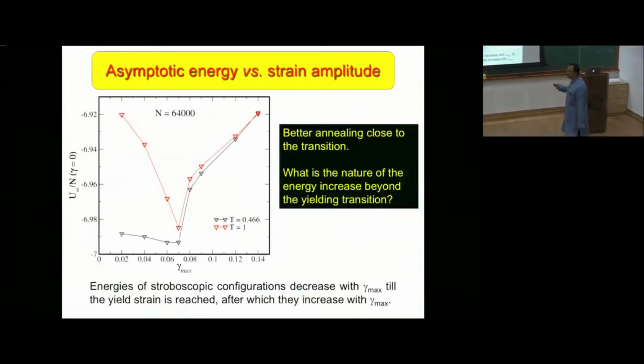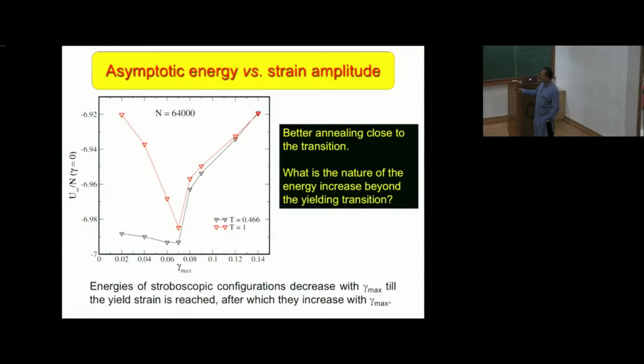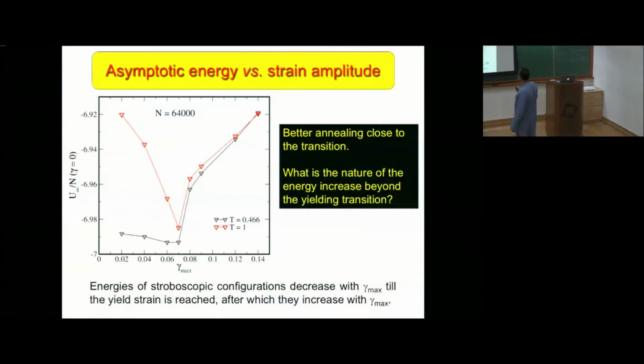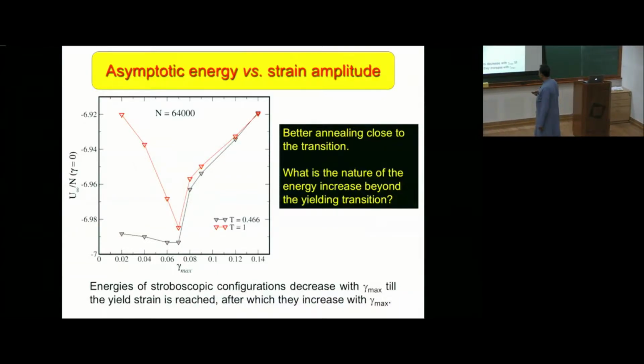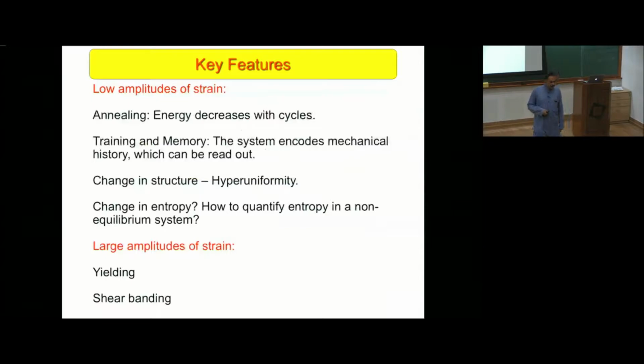So this is now the summary of what we said about the annealing behavior. Below yielding, you always anneal better and better as you increase the amplitude of deformation. Above, you don't. But on the other hand, above the transition, you seem to have a quote-unquote ergodic state, in the sense that the final properties of the system don't seem to depend on initial conditions, which is not true below the yielding point. So what's the nature of this energy increase is the next question.